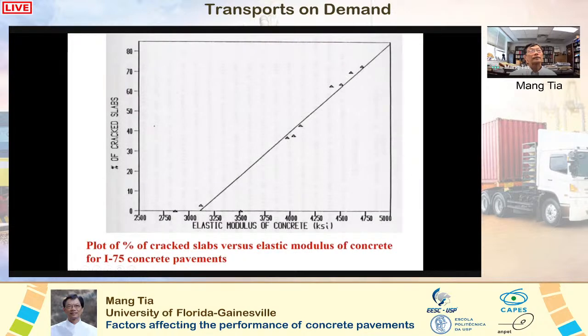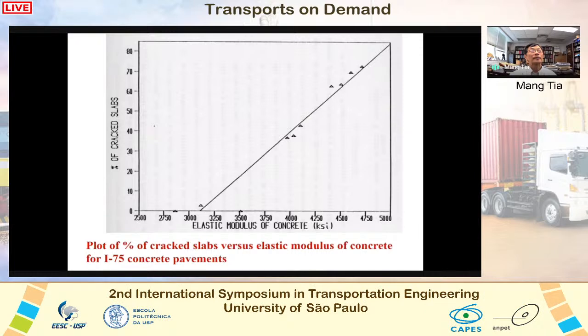The maximum stress is affected by the elastic modulus of the concrete, as shown in the previous slide, and the data obtained from I-75 concrete pavement in Sarasota and Manatee counties show that the concrete with higher elastic modulus show higher percent of cracked slab. These are data from our field observation. When we plotted elastic modulus of the concrete versus the percent cracked slab, it shows that the concrete with higher elastic modulus actually cracked more.